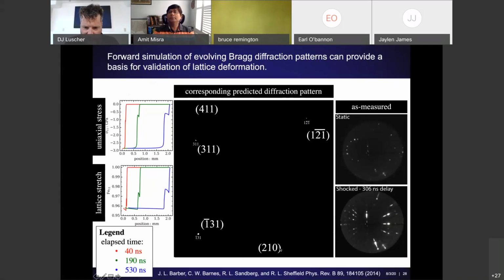So this big black region in the middle of the screen is a simulated diffraction pattern at different times as we shock compress the material through some deformation history. And then on the right is the same material, and those are experimental diffraction images. The static image is before a deformation process, and then the bottom image is under a shock after about 300 nanoseconds after impact, which is somewhere in between the trajectory I looked at. You probably noticed these don't really match up that well, and that's because they're actually not the exact same conditions. It's not like for like,